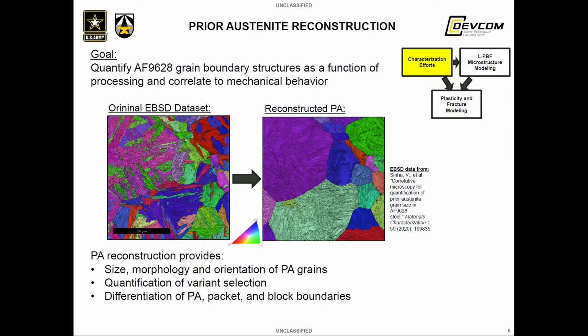Prior austenite reconstruction is a useful tool to have when trying to link final microstructure and properties to the process. In laser powder bed fusion, the austenite structure is an intermediate stage because austenite is typically only stable at high temperatures. And so it can't be imaged in situ.